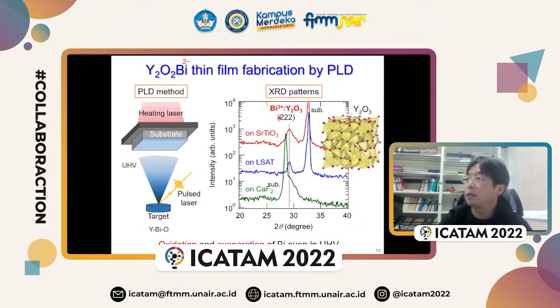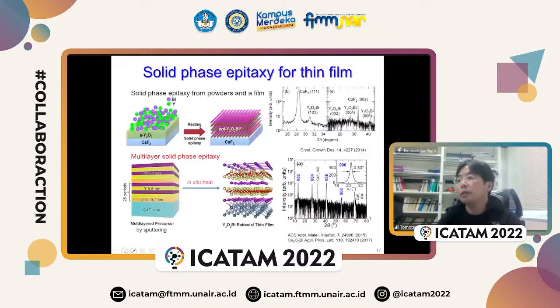In this case, as I told you, this bismuth has an unusual valence. This is a 2- ion. So by using this method, we always obtain not this compound, but the trivalent bismuth compound Y2O3. This is also a very stable compound. So anyhow, it is difficult to obtain negatively divalent bismuth by using pulsed laser deposition, even in ultra high vacuum. So we developed a different method.